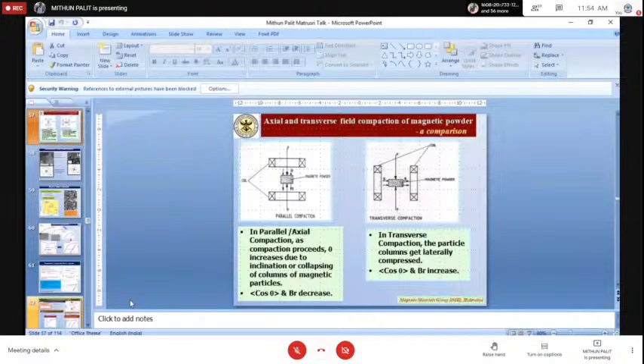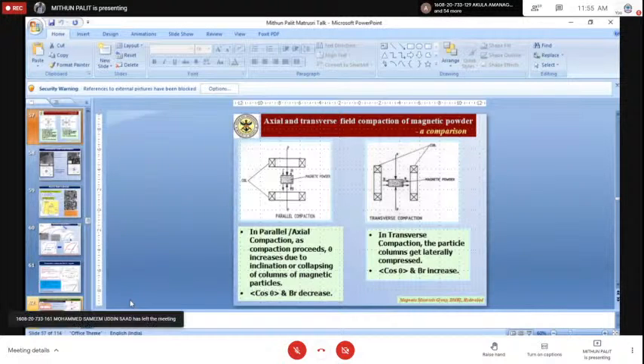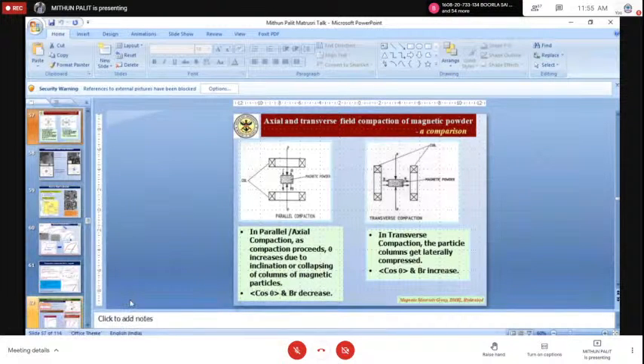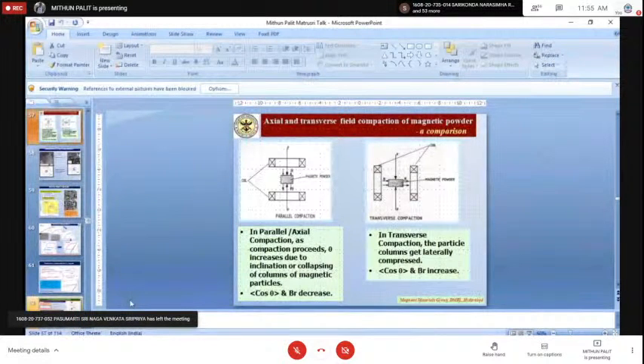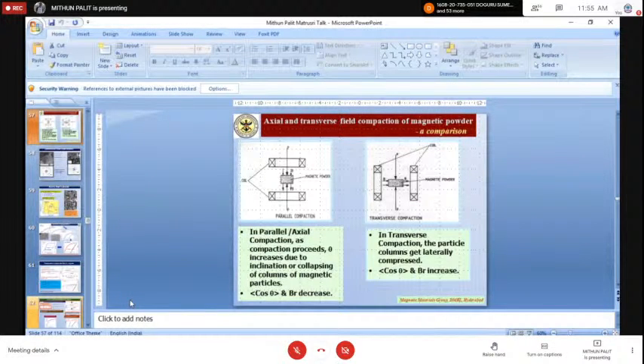In the left side one, the magnetic field of the electromagnet and the pressure applied to the powder are parallel to each other. Whereas in the right side one, the magnetic field applied and the pressure applied are orthogonal to each other. The benefit of the right side machine is that when you apply the pressure, it will try to destabilize the orientation formed in the material. Whereas if the magnetic field is applied in the direction away from the pressure direction, then by pressure we are consolidating the orientation achieved by the magnetic field.